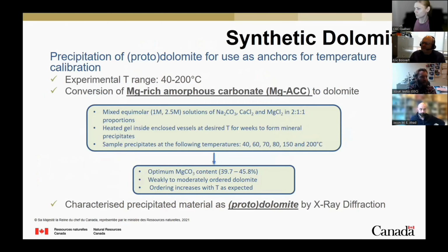Now Ben has done quite prolific work in cooking dolomite. Basically, what he does is mix equimolar solutions of salts to bring calcium, magnesium, and carbonate, bicarbonate together in order to produce an amorphous gel that is a kind of high-magnesium carbonate, which he then heats at the target temperature for weeks. That allows some mineral to crystallize, which we check at the GSC Ottawa in the mineralogy lab with X-ray diffraction. We realized that we were actually getting weakly to moderately ordered dolomite, which is great. It's not quite dolomite, it's proto-dolomite. We don't have the crystallographic ordering that would be necessary for calling it a proper dolomite. But it doesn't matter because the isotopic bond ordering is not influenced by the crystallographic ordering, and we can use them as calibration material.